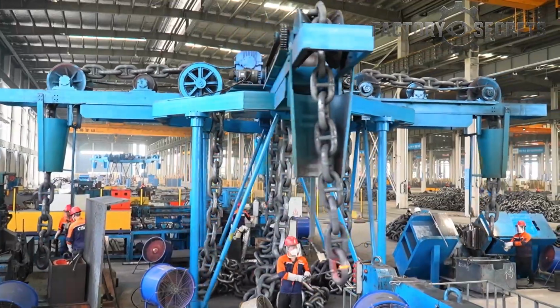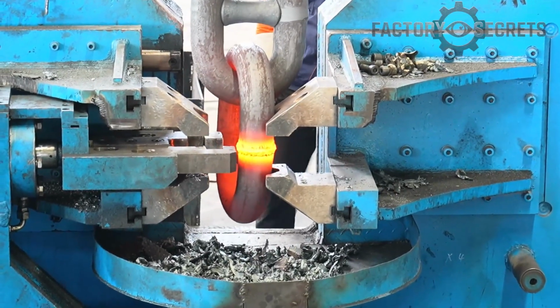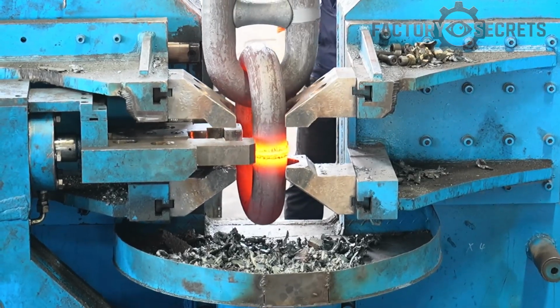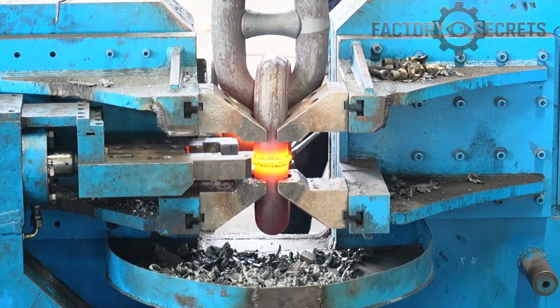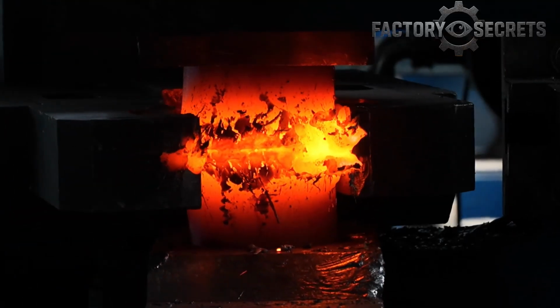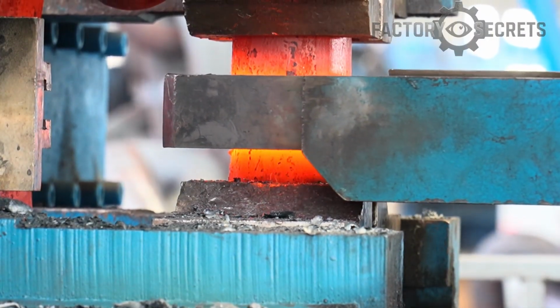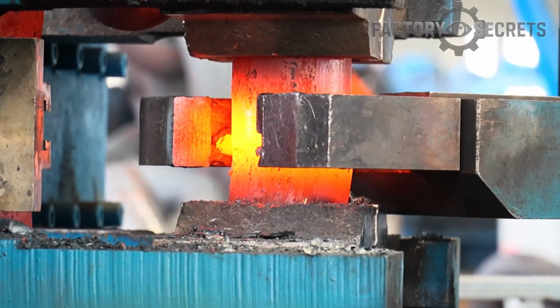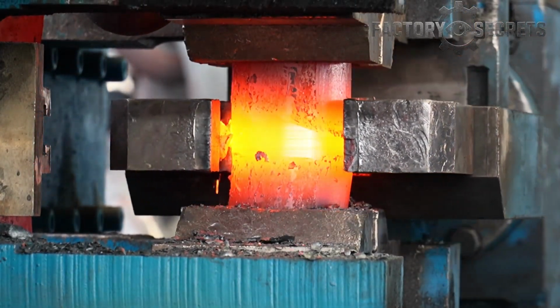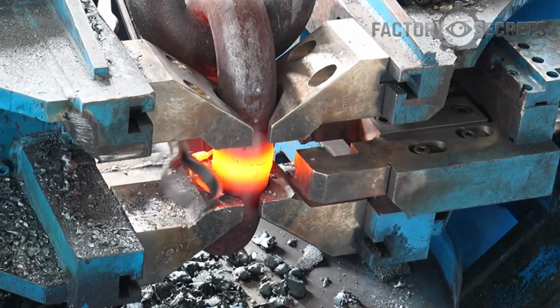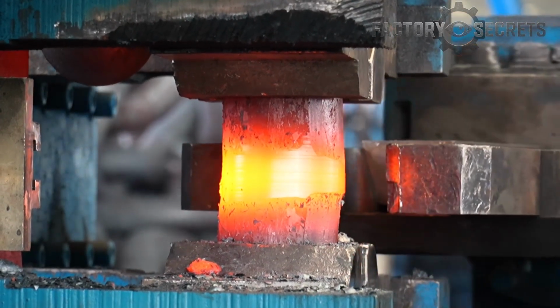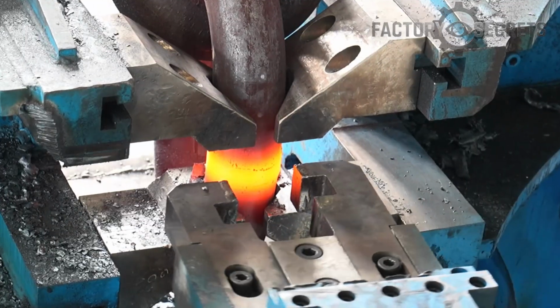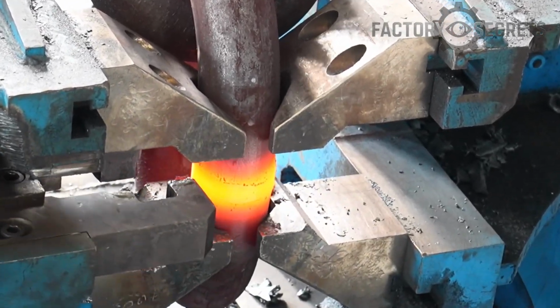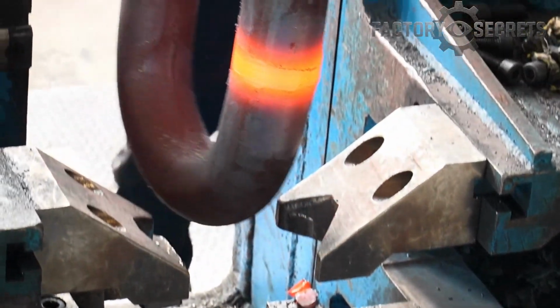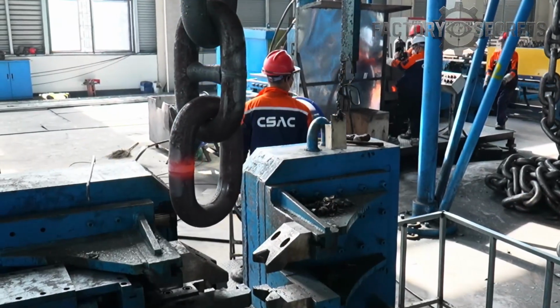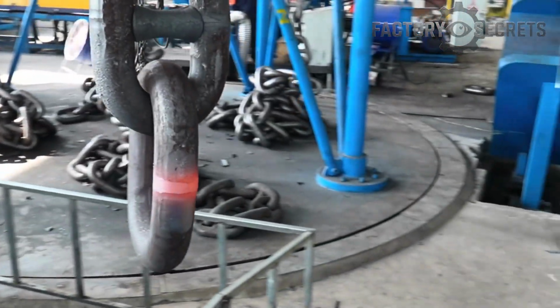The welded link now moves to the trimming machine, where the excess metal from the weld, called flash, is mechanically removed. The result is a link with a smooth, uniform surface at the joint. No bumps, no ridges, no weak spots. It looks as though the weld was never there, which is exactly how it should look. A chain that passes through sheaves and windlass machinery on a ship needs to be smooth. Any irregularity can cause drag, wear, or failure at the worst possible moment. The trimming stage ensures every link meets that standard.